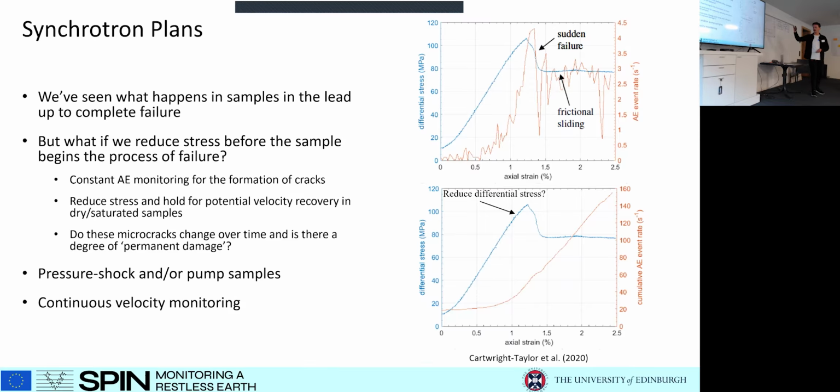This is some results from Alexis's work, where she was passively listening for acoustic emissions, and noticed that there was a very high acceleration of these acoustic events that would occur in the lead up to failure. So we think by monitoring, as soon as these start to accelerate, we could maybe reduce differential stress and see what happens at the grain boundaries and at these micro cracks. Do we see healing? Do we see anything at all? But if we don't, at least it gives us a sense of the scale at which these events occur. And then all the while, we'll be measuring velocity as well.